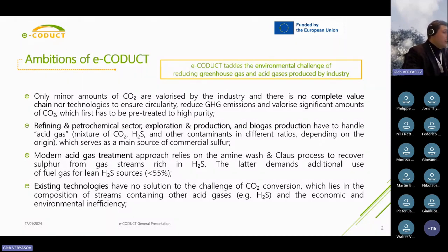The approach which industry uses for acid gas treatment hasn't changed so much in the last 100 years. It's still amine wash followed by the Claus process, where hydrogen sulfide is burned to basically produce water and sulfur. There are different variations of the process, but in principle it relies on combustion followed by several catalytic sections where SO2 is reacted with H2S to generate sulfur.